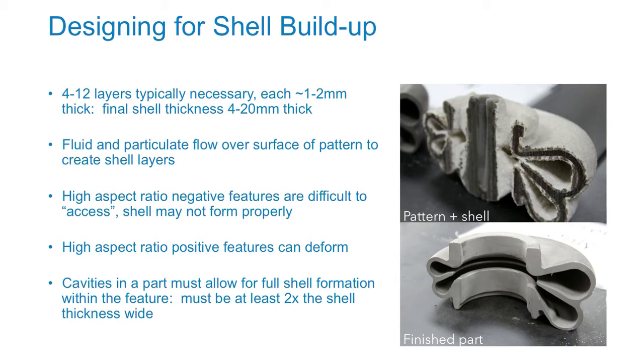So you can see what a shell built up around a wax pattern looks like up top there, and then what the finished casting looks like. With these turbine blades here, there's generally a bit of rotation during the dip process to make sure that you get that even coat. Another thing to consider is that the pattern has to survive the shell buildup process without deformation.